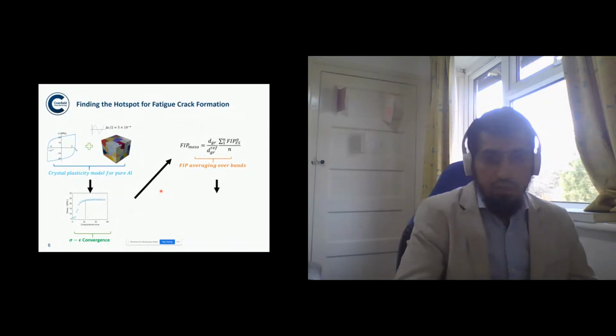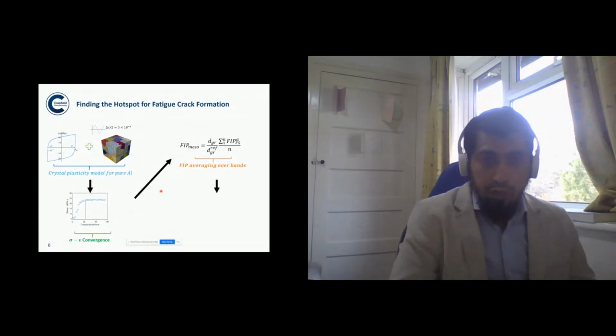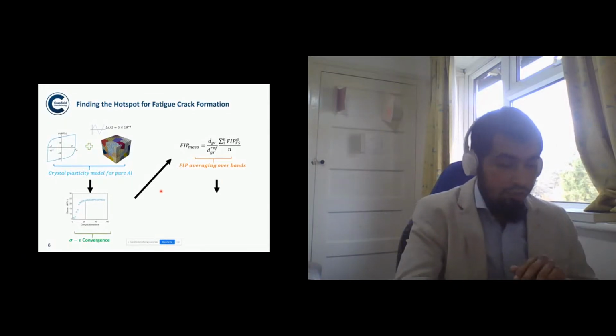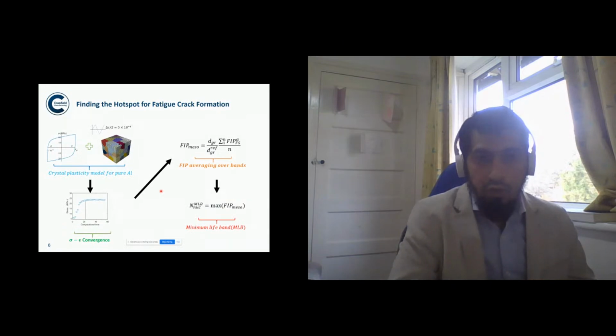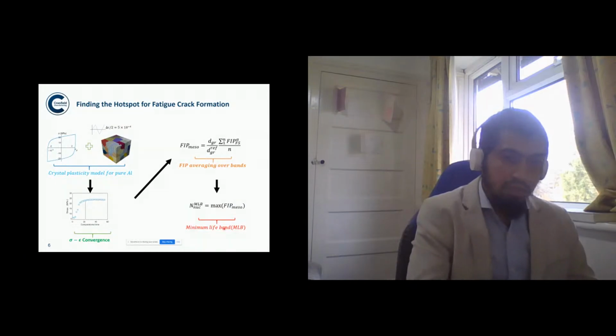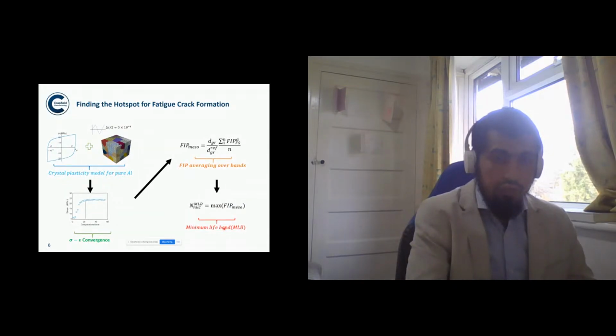The next step is to find which band among all the bands has the maximum value of average FIP. And this is what we termed the minimum life band. So only the one band with the maximum value of the average FIP is the minimum life band. And this is considered to be where the crack initiates.